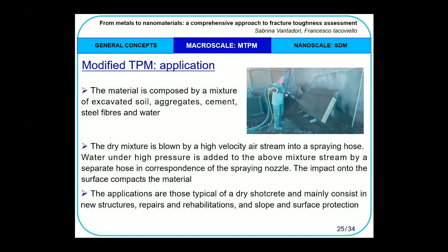But now let us move to the application of the proposed procedure to an innovative earth-based material. The material is composed of a mixture of excavated soil, aggregate, cement, steel fibers, and water. The dry mixture is blown by a high-velocity air stream into a spray hose. Water under high pressure is added to the mixture stream by a separate hose at the spray nozzle. The impact onto the surface compacts the material.